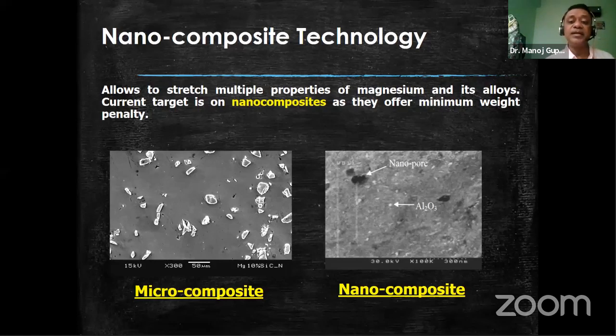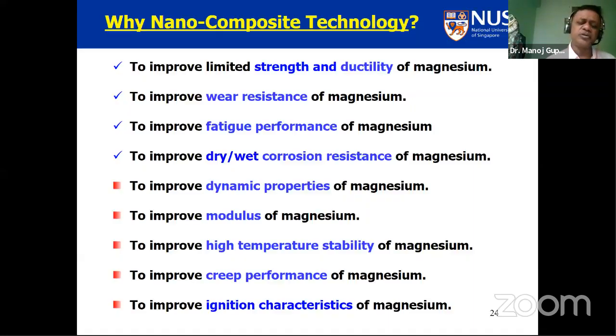This size and length scale of the reinforcement makes a tremendous difference in the properties of magnesium. We use a nano reinforcement because it has the capability to improve the strength and ductility. It can improve the wear resistance, the fatigue performance, and the dry and wet corrosion resistance. These first four properties are very important for bioapplications. For engineering applications, you can add these four properties to dynamic properties, modulus, high temperature stability, creep performance, and ignition performance.